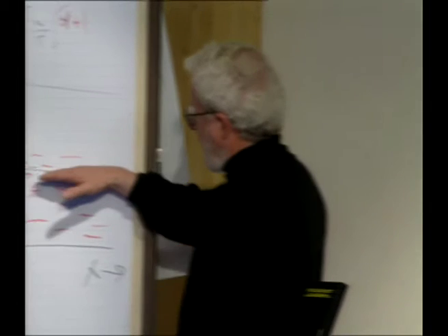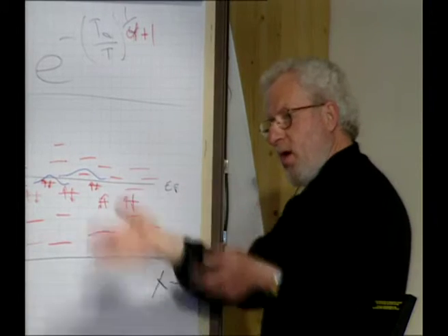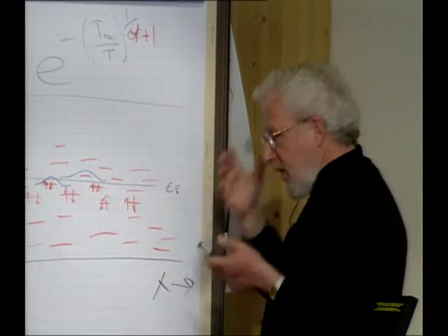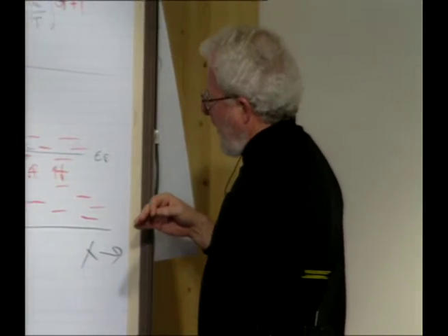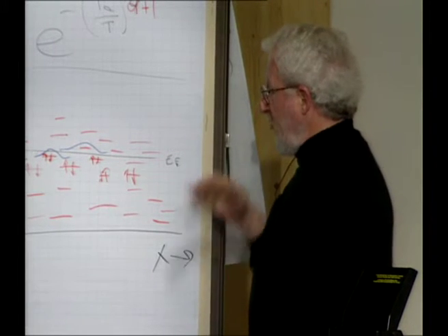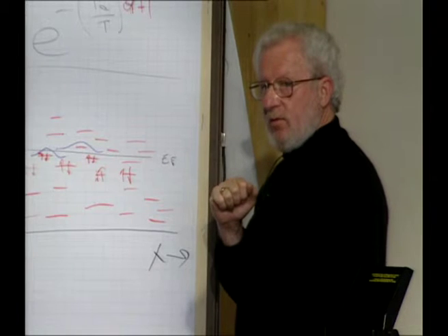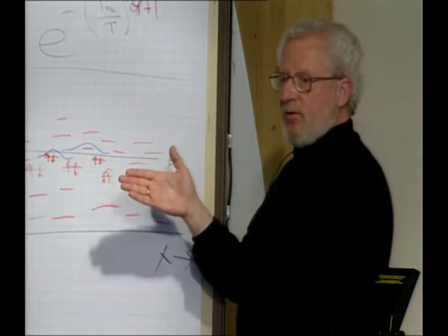So now we have a mechanism for electrical conductivity if I have localized states. Okay? And I went through all of that because I do experiments at real temperatures, not at T equals 0. The metal insulator transition is a 0 temperature phase transition, and I'm going to show you that one can study that, one can observe that. When you're on the metallic side of the metal insulator transition, you've got extended states, and electrons can move. When you're on the insulating side, you've got a Fermi glass, and nothing can move at T equals 0.